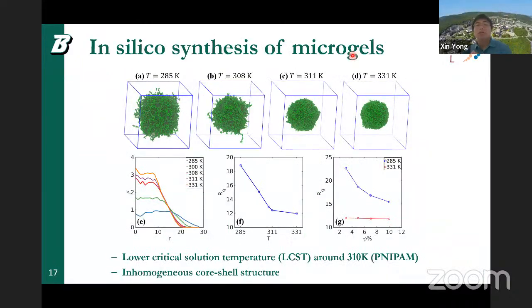Okay, so we have done this in the past. When we worked on this hydrogel, we rigorously considered the chi parameter, and this chi parameter is parameterized against experimental data in terms of its temperature dependency, and then we convert the chi parameter to the DPD parameter. Now, I know there's a lot of debate on the degree of cross-linking, and it's dependent on the DPD parameters. So here we're still doing things in a fairly traditional way, where we just consider 25 kT, for a density of 3. But what we're trying to do here, especially for these gels, is we measure the collective diffusion of the chain within the gel,